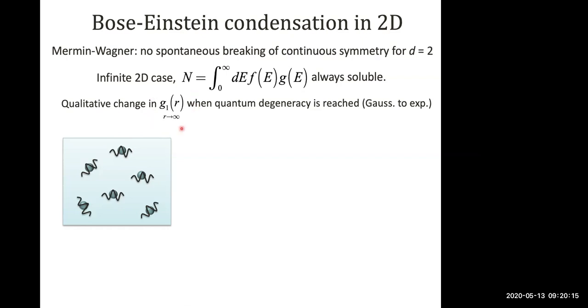But nevertheless, if you look at the first order coherence, you find that as you increase the number of particles, once you reach quantum degeneracy, which corresponds to the situation where the de Broglie wavelengths of the individual particles start to overlap, you have a qualitative change in the behavior of G1. So the coherence function goes from Gaussian to exponential. So you have an increase in the coherence length.